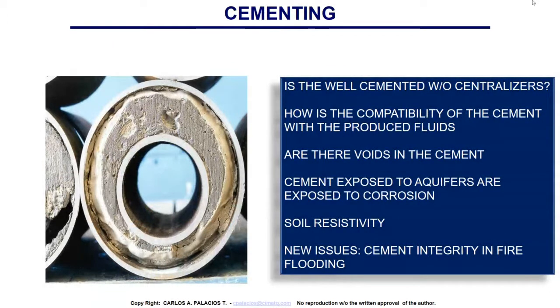Cementing, well, from my point of view, cement is the first barrier that we have for the casing. If we look at concrete structures, reinforced concrete, the rebar in the concrete is well protected because of the cement outside. The pH of the cement, similarly to the cement that we use in the oil industry, is around 10 to 12 to 13. At that high pH, the rebar, the casing passivates, and therefore corrosion is somewhat controlled. But what is the quality of this cement? Is the cement completely all the way around my casing? I don't know. So that is the first barrier. What is that quality? Because much of the cement is going to be exposed also to aquifers. So is that quality going to be protecting the casing externally?